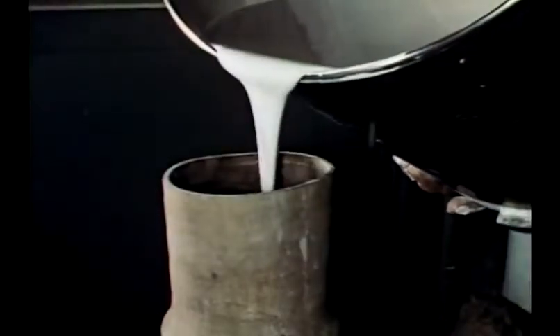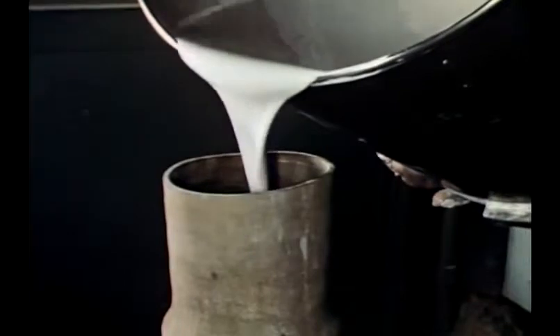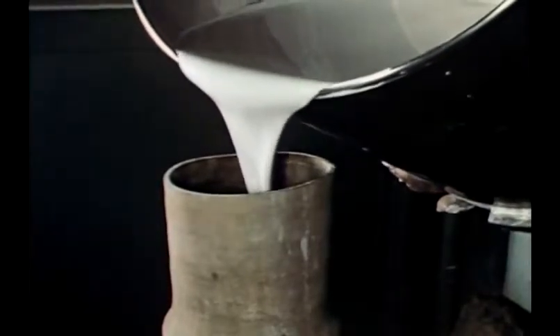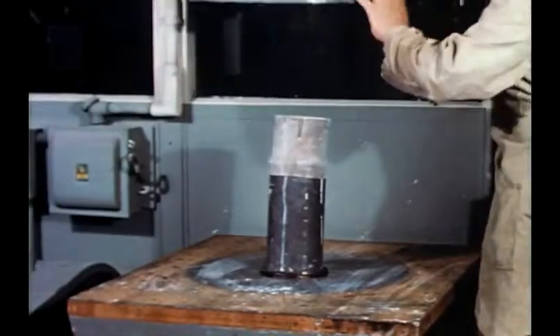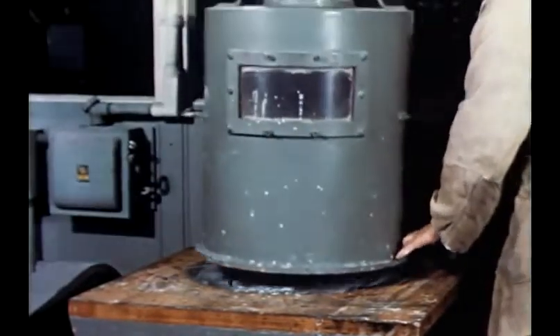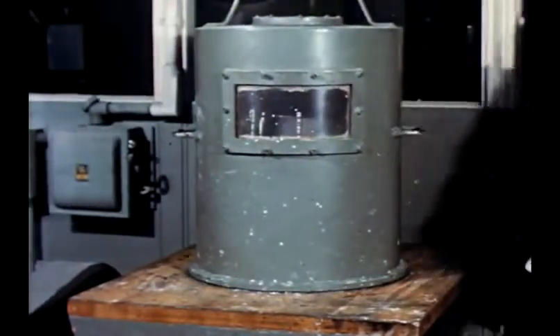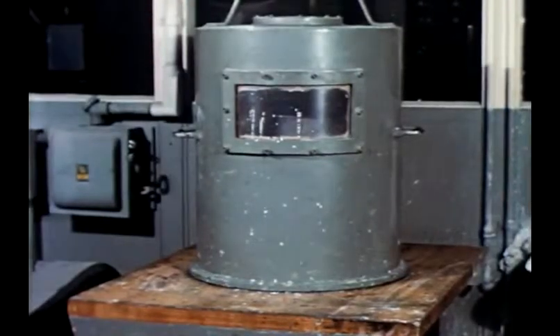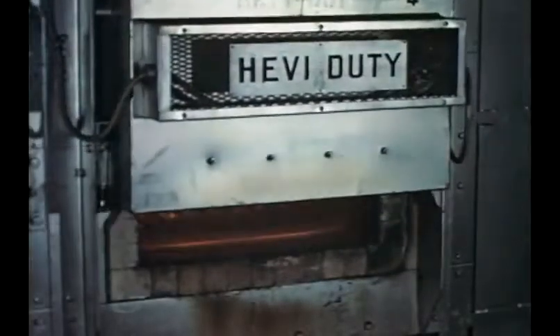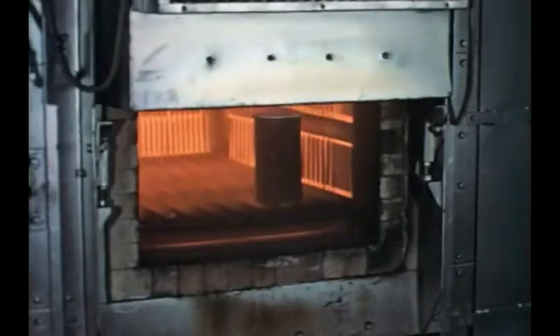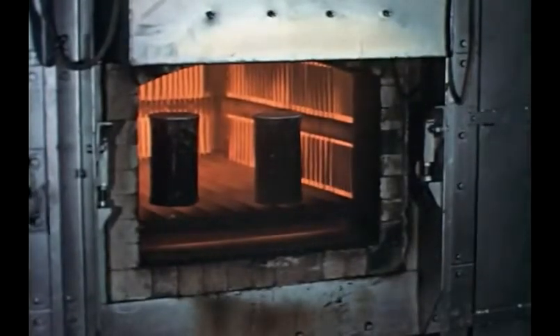When the investment is thoroughly mixed, it is poured into the flask and around the wax pattern assembly. The flask is then placed in a vacuum chamber to remove air from the mix. After investing and air drying, the molds are placed in a furnace. Here the drying is completed, the wax is melted out, the wax residue is burned off, and the mold is cured. During this furnace cycle, the temperature is gradually increased from room temperature to 1900 degrees Fahrenheit.